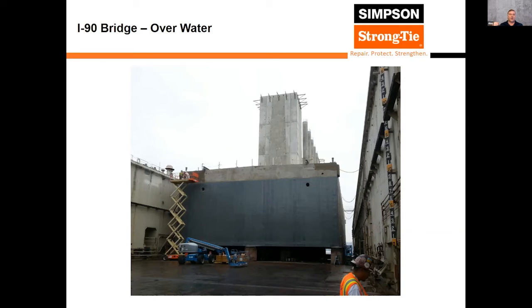So the PT strands are there to keep everything under compression as it deflects, so the concrete stays in place. The nice thing about PT is it functions a lot more like a spring to reorient the structure back to where it's supposed to be, as long as it's never exceeded its capacity. These PT strands run through the entire pontoon structure, and the pontoon structure did not have a plan for that originally. So there are lots of concrete bulkheads in the way, and we needed to core new holes to string the strands through the pontoon structure, and those new holes need FRP or some form of reinforcement around them. FRP was the solution chosen on this project.